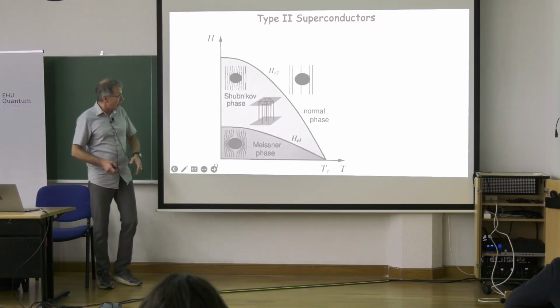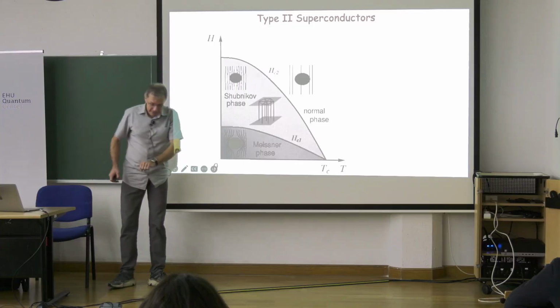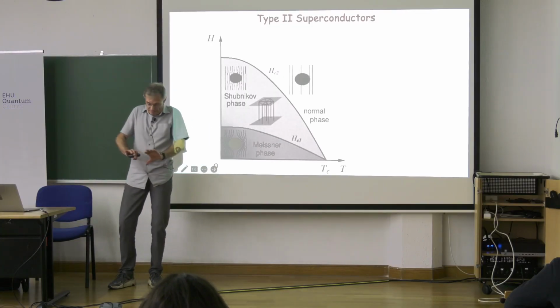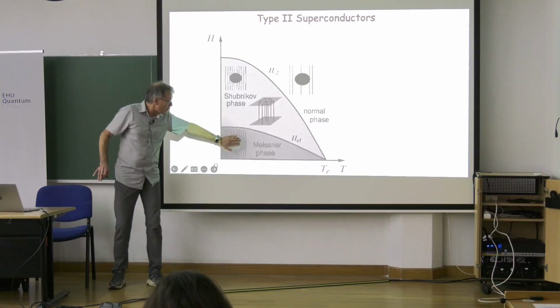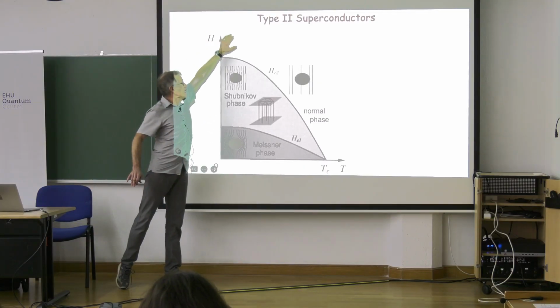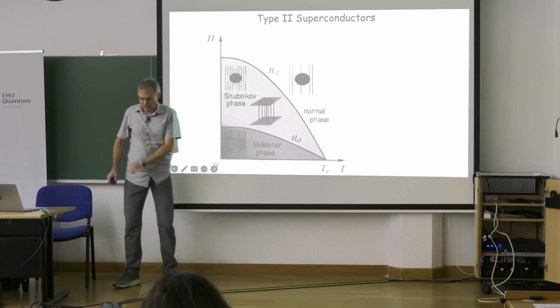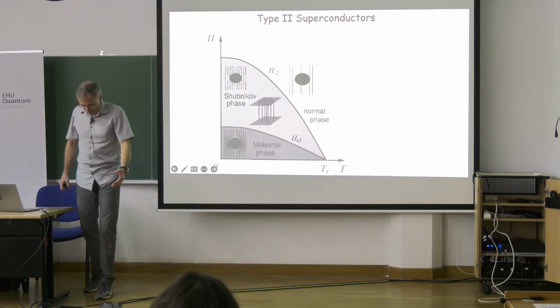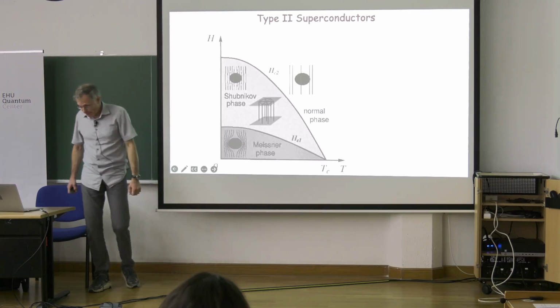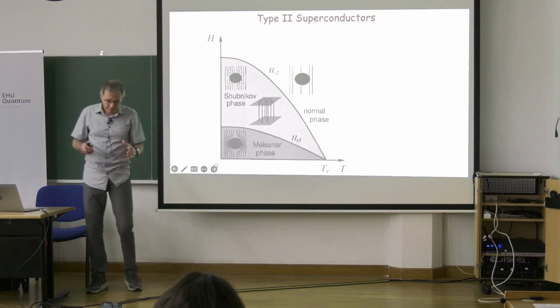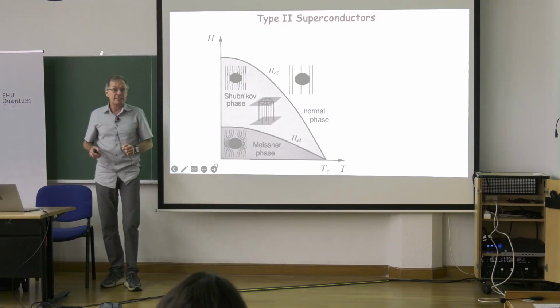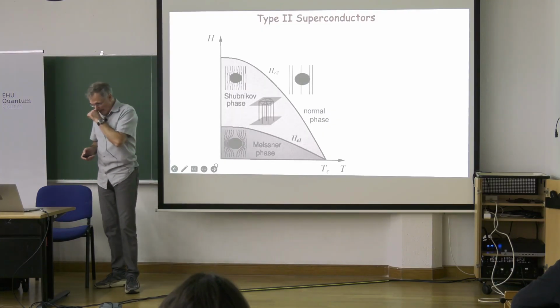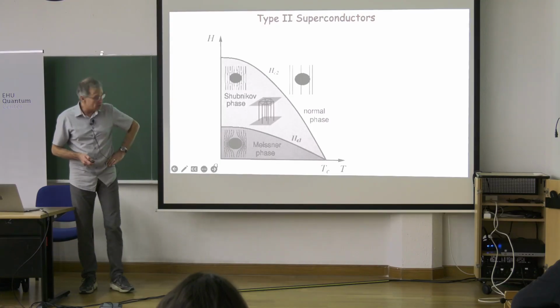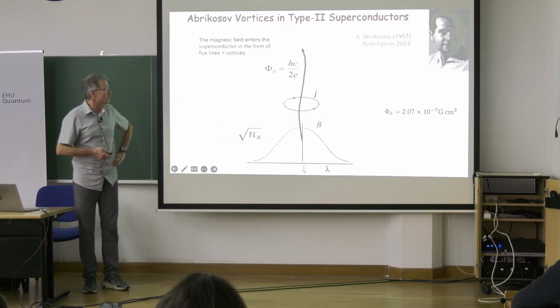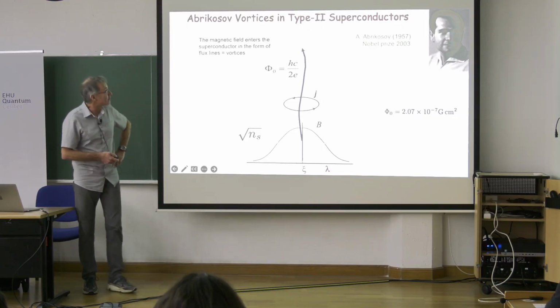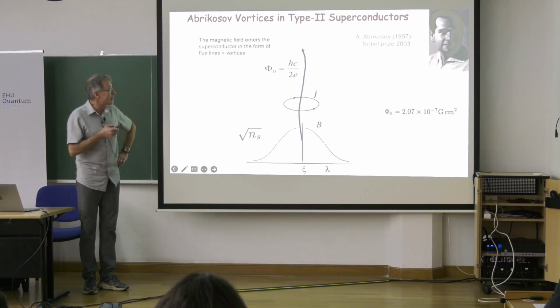So then the Meissner phase, which is the analog of type 1, where magnetic field is out, is at low field. Normal metal is at high field, and in between there is the so-called Shubnikov phase, where magnetic field penetrates the superconductor but doesn't destroy superconductivity. And the understanding, or invention in a sense, was due to Alexei Abrikosov,